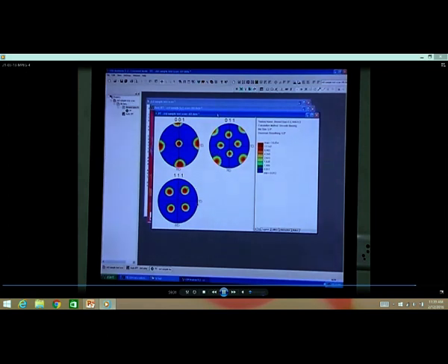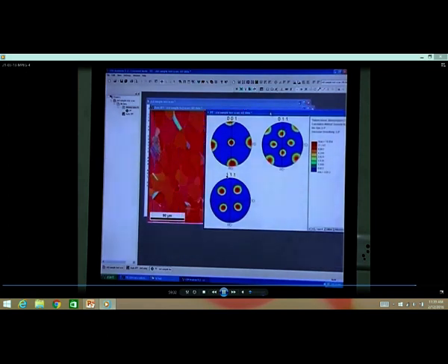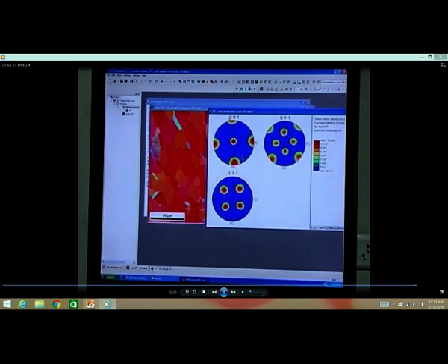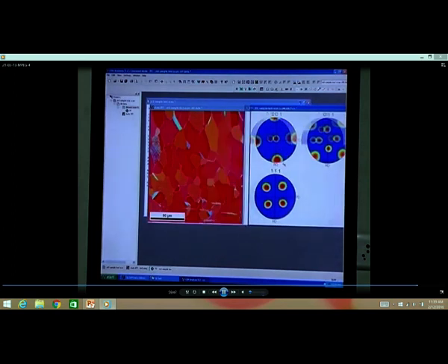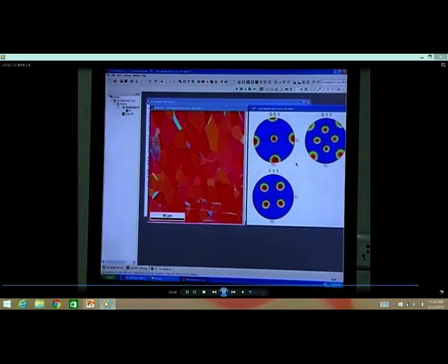So, this is a very nice pole figure, showing a cube texture 0, 0, 1. Any material which exhibits cube texture will show a pole figure of this kind with 3 different orientations here. In this case this is a nickel sample where the student processed it to obtain this cube texture.